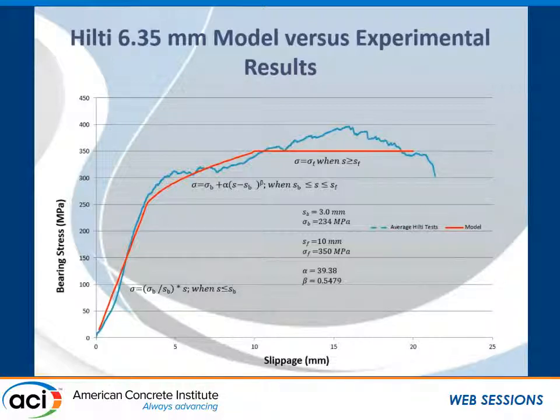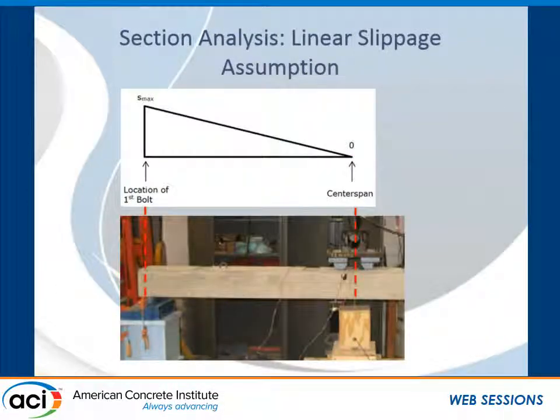Once we had our bearing slip relationship defined for the connection, our next objective was to combine it with load deformation constitutive equations to predict the behavior of MF-FRP strengthened beams. And a process was developed to determine the nominal moment capacity of the cross-section, assuming that the slippage that occurs between the FRP and the concrete varies linearly along the shear span. See here. Maximum slippage was assumed to be located at the bolt furthest from the center line of the beam. And although we did assume a linear slippage for the purpose of this study, it would be an easy matter to incorporate a different slippage span relationship into the analysis.